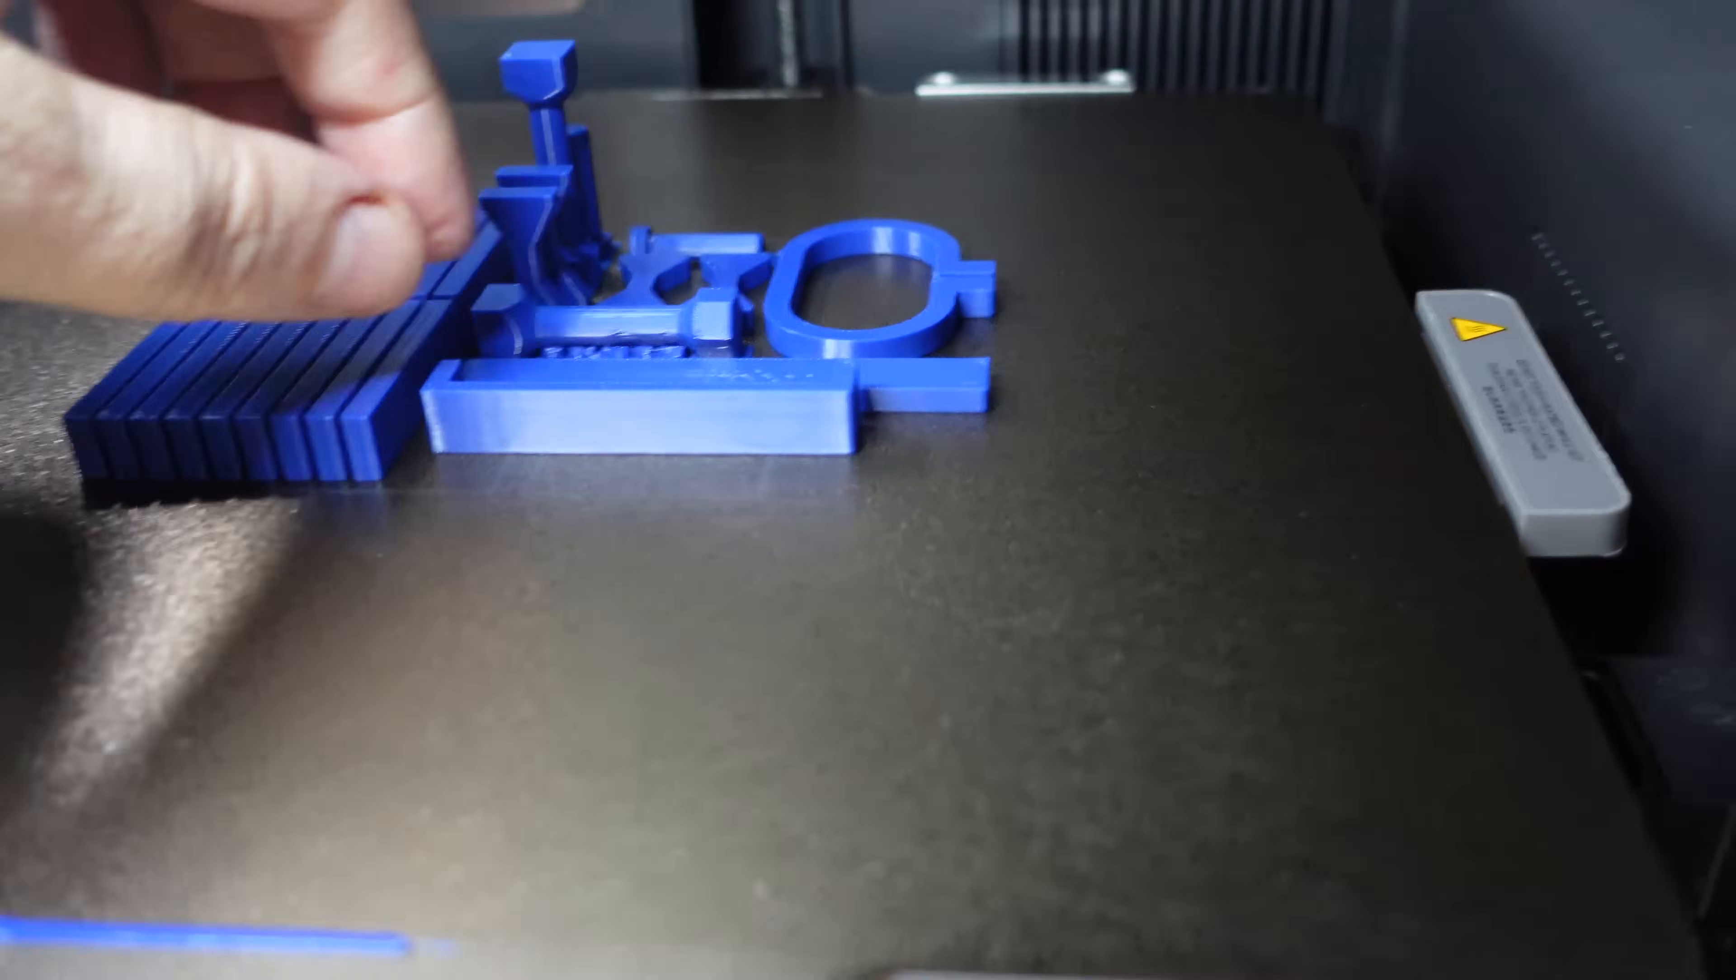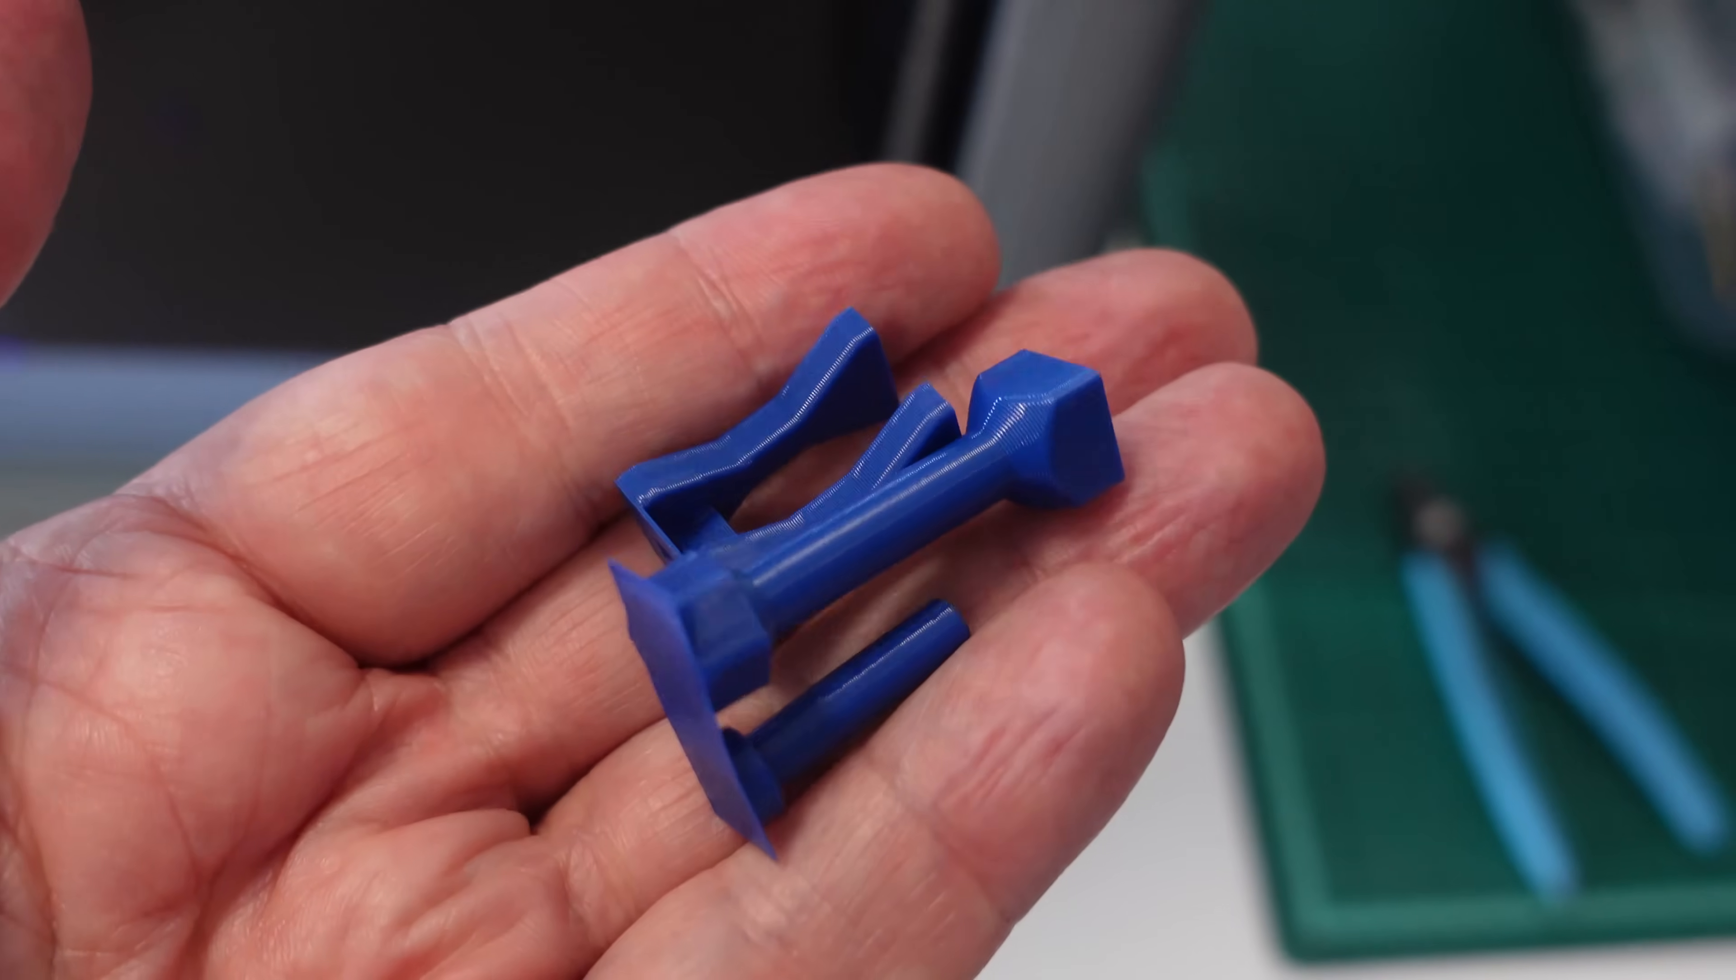10 more minutes of printing. These are the last vertically printed objects, and the maximal air temperature inside was 42 degrees Celsius, and the printing is really nice. The printing is finished, and those overhangs look really nice. This is my reference for the print quality. Now let's check the bed adhesion. It is very good until it's hot. I wait until it cools down. The bed is 35 degrees Celsius. Now let's try to remove it. Great. And look at the quality of these overhangs. Perfect printing.